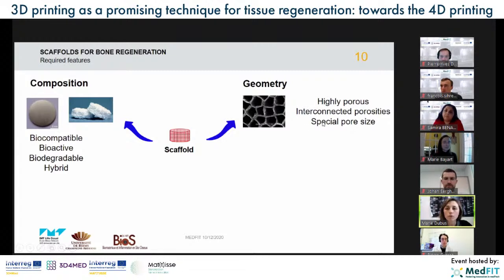And also a crucial parameter of the scaffold, its porosity, because the porosity allows the invasion of cells inside the scaffolds. And we have to choose the good pore size in order to have the right cells inside the scaffold. And moreover, the cells inside the scaffold need to be fed. So the pores need to be interconnected in order to allow the exchanges of fluids and nutrients to the cells.